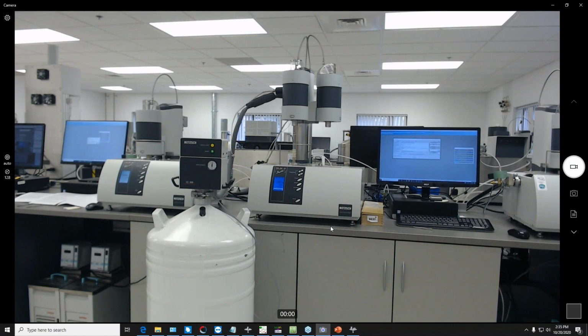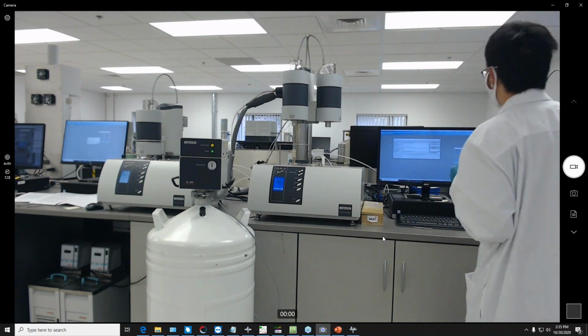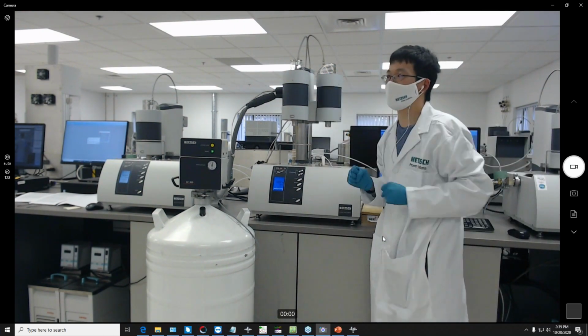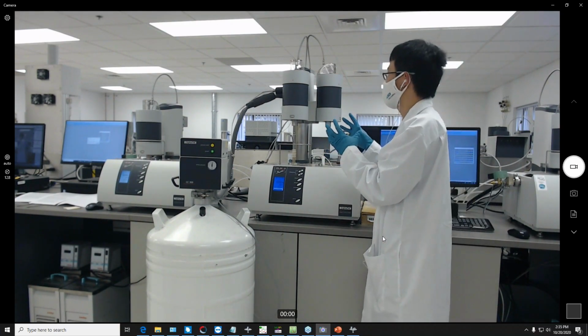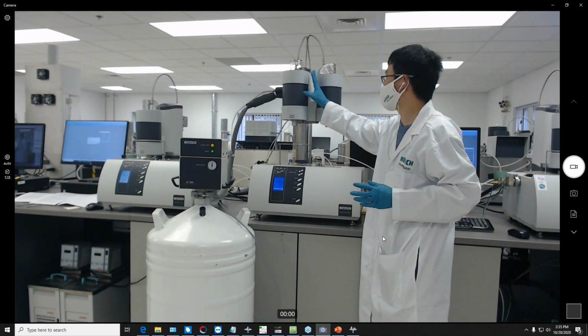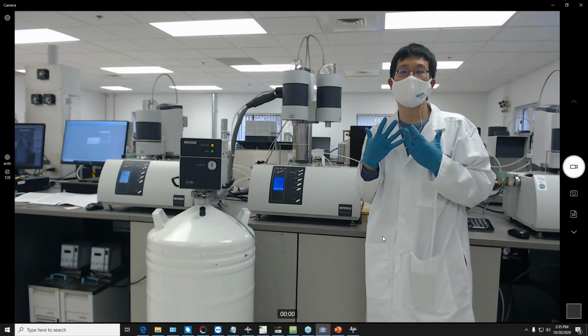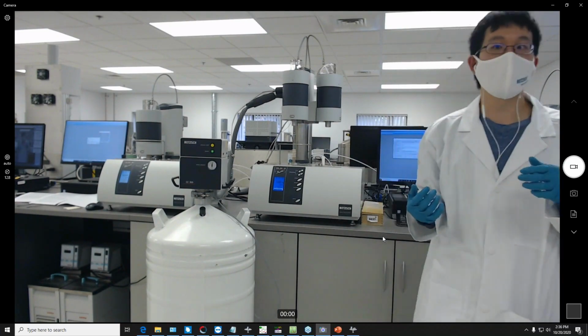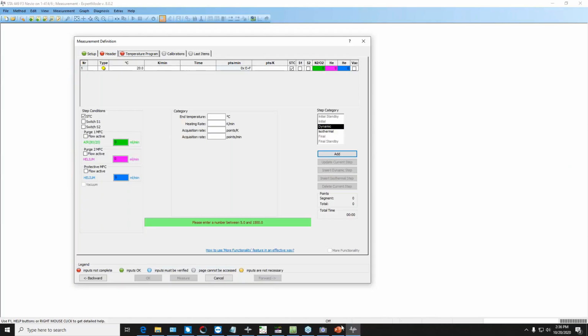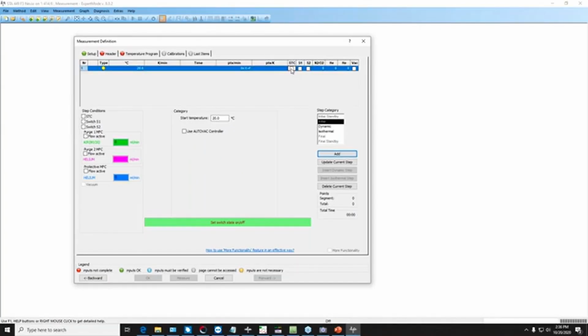How could I improve DSC signal in a heating, cooling, heating cycle? Our STA units have what we consider a large thermal inertia furnace, in which it takes a little bit of time for the heat to transfer from the heating elements to the sample stage. In terms of trying to create a more reproducible profile, we recommend that you disable the STC function on your measurement runs. If you see on screen right now, I have an STC column in the temperature programming. Normally we recommend you turn the STC option off during these STA runs so that you utilize the furnace's thermocouple to translate the heat to the sample carrier, whereas the STC function means that the instrument is trying to control the temperature at the sample carrier level.